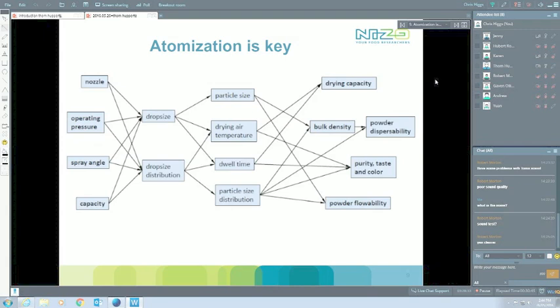So what we typically find is that controlling atomization is really the key to controlling powder quality. Really knowing about what product is going in, and thinking about how it is going to behave during atomization, because unfortunately you cannot measure a lot at actual atomization conditions. Timescales are so short and shear is so high that you cannot really mimic it. So it's really about taking the right data and extrapolating that to atomization conditions, and that's where we end up being able to control our product and our process as much as possible.